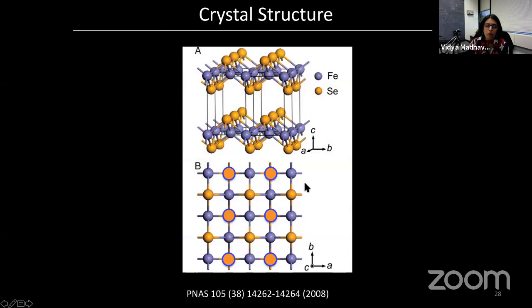Okay, so what do you expect to see when you do STM imaging on the system? Well, the material is very layered and it cleaves very nicely. So it would cleave between these iron, selenium, tellurium trilayers. So it would cleave right here. These top atoms are tellurium. So what you expect to see is just these top atoms, which form a square lattice.